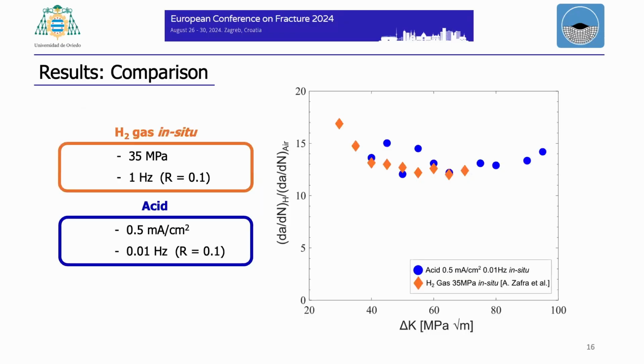We also have this comparison. In this graph, we have the ratio of the growth rate in hydrogen and the growth rate in air. And you can see that from 40 to 80, the behavior is the same. The growth rate in hydrogen is like 13 times faster. And we were able to have the same behavior as for the gas test.